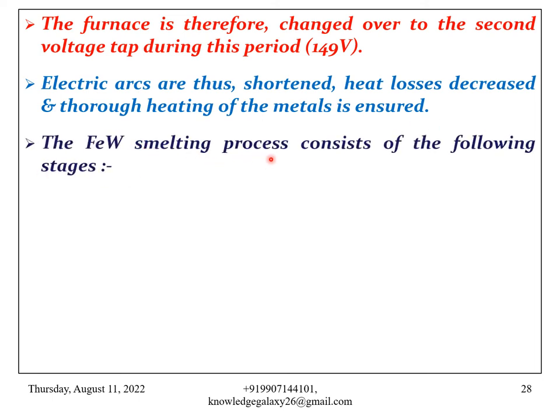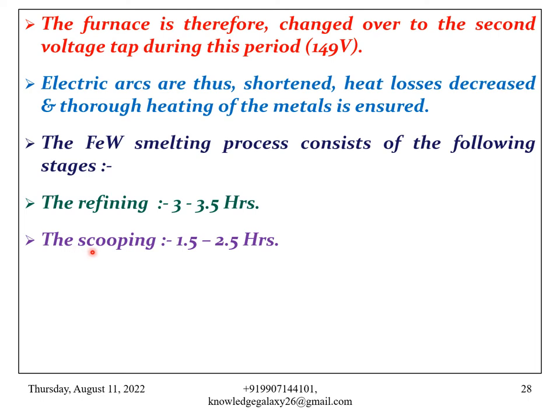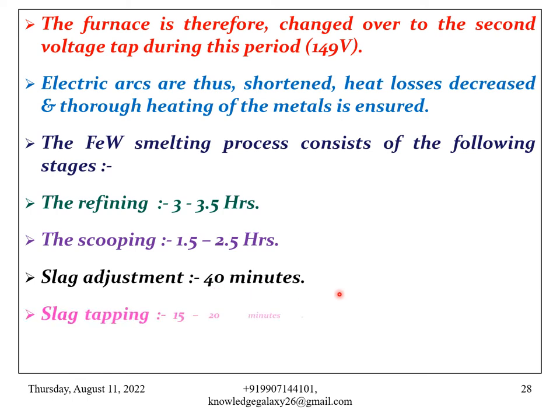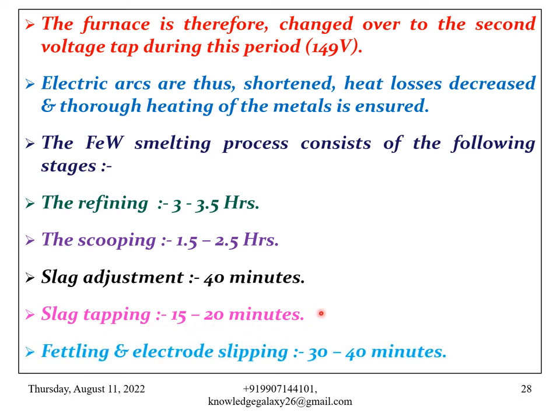The ferrotungsten smelting process consists of the following stages. My dear friends, these are the various technical parameters and stages in the production of ferrotungsten. The first stage is refining, which takes 3 to 3.5 hours to refine the alloy from impurities. The next step is scooping. It takes 1.5 to 2.5 hours. The next stage is slag adjustment, which takes approximately 40 minutes. The next stage is slag tapping. It takes around 15 to 20 minutes. And the final, last but not the least stage is fettling and electrode slipping, which takes 30 to 40 minutes.